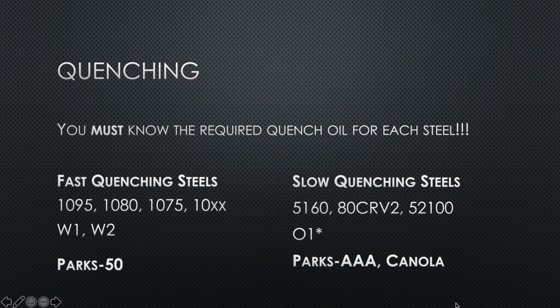1095, 1080, the 10 series, W1, W2 require very fast quenching speeds. They need to be quenched in less than a second, meaning the temperature needs to be brought down from the austenitizing temperature to below 500 degrees in less than a second. So you need an oil that will quench it that fast. Other steels cannot be quenched fast. If they are, they will crack. 5160, 80CrV, 52100, especially O1, need a slower quenching oil, something like Parks AAA or even canola.